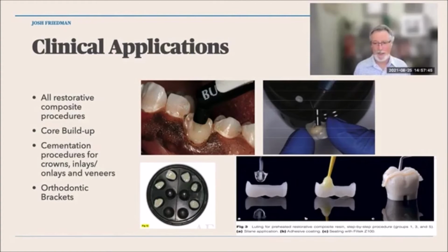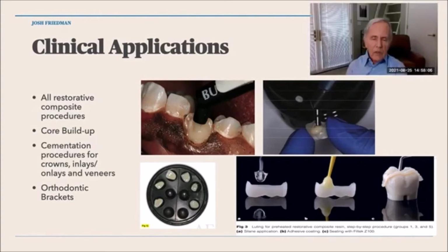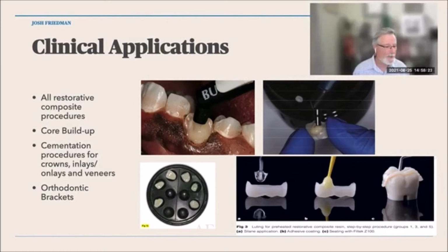In fact, recently I saw an article where they compared the warming of composite to the use of a dual cure cement, which most dentists use in the posterior. They'll use dual cure cements. And I was astonished to see that the film thickness was better, the color stability was always better. Well, I think that was the article by Pascal Magne that you're referring to. And I think they also found out in that article that the crowns that they were placing seated better using this technique. Yeah, that was really impressive when I saw that.